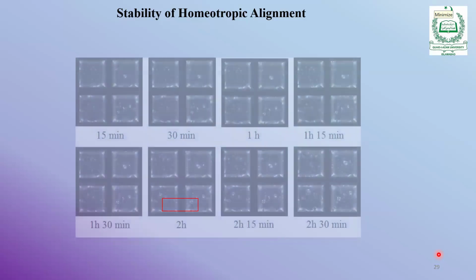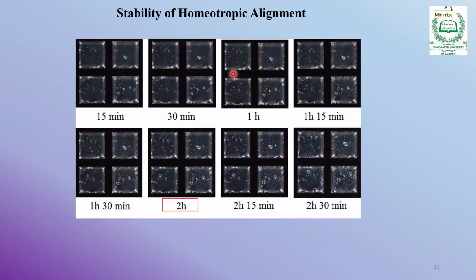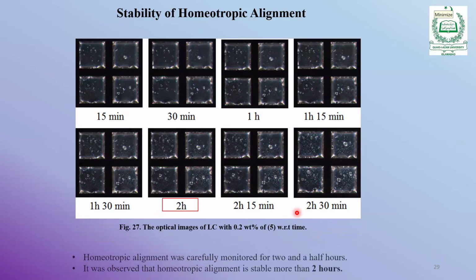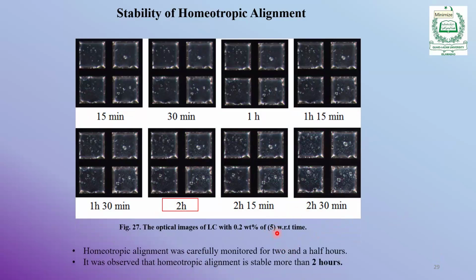Now the stability of homeotropic alignment. So once we have reached the homeotropic alignment, this homeotropic alignment should be stable over a span of time so that we can perform the next experiment, or we can check what happens when we add the analyte, right? So this homeotropic alignment should be stable for some time. So you see, we have observed this homeotropic alignment for more than 2 hours, and this is the result with the first amphiphilic ligand. So you can see that the homeotropic alignment is same, constant at least for 2 hours,